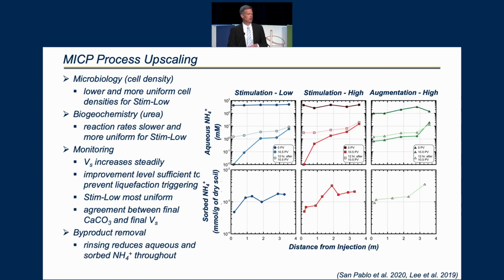The final one is byproduct removal, and this is the final step through the treatment process, and you can see in this case systematic reductions or lowering of the contours of the ammonium, and that also corresponds to reductions of the sorbed ammonium to pretty low levels.